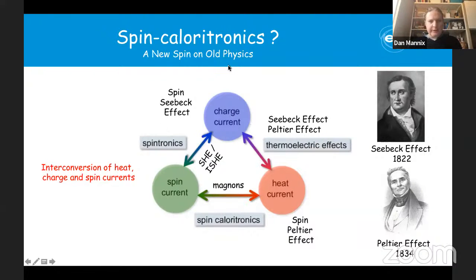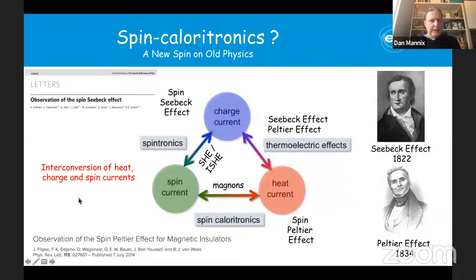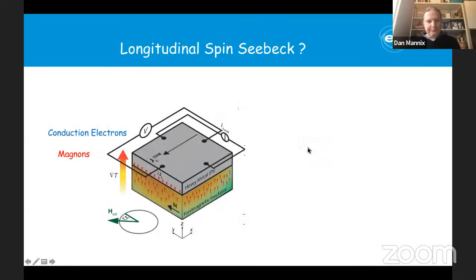Where we go into spin-caloritronics is that we can actually use magnons to create a spin current and then transform that spin current to charge current using spin Hall effect and inverse spin Hall effect. So you can basically go around and get these interchange going via the spin current. And that can give a huge diversity for new device applications in the future. So this is why these materials are being studied quite intensively at the moment. So the observations of spin-Seebeck effect have really come around in the last 10 years or so. Spin-Seebeck and spin-Peltier are analogues of these classical physical phenomena.